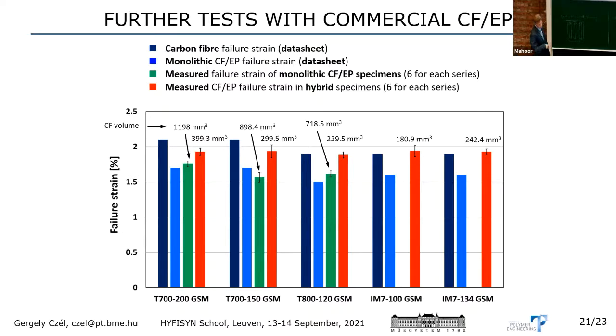And with the hybrid specimens, we are actually approaching the fiber failure strains reported in manufacturers' datasheets, which doesn't mean that it should be a baseline, because actually these fiber failure strains are based on impregnated tow tests, which I think is a little bit, let's say, not very well defined as a test. So we don't actually know how many fibers, how thick bundles, and how it was actually tested. But for sure, these are not individual fibers tested. So don't take it as a baseline. I just report here as something to compare my results against. But I think we are going to the right direction with these hybrid specimens.